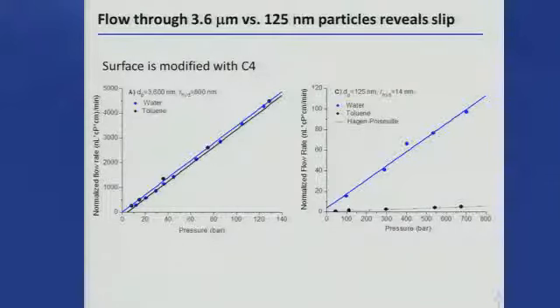And so if you're able to go down to 125 nanometer particles, you can get this 20-fold enhanced flow rate, which is really amazing. It actually makes it feasible to start thinking about using ridiculously small particles in HPLC. The reason why people had stopped at about 1.7 was because the calculations tell you that the resistance to flow is prohibitive, and you're not going to do any better when you go smaller. But now this tells us no, you can go to smaller particles and still get good flow rates. And in addition, there's something else going on that some of you might have thought about already as I'm talking here.